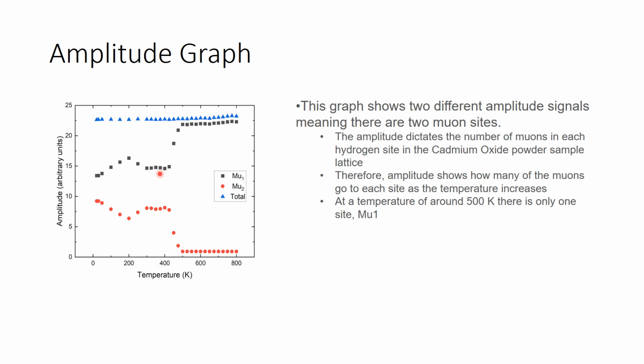As the temperature increased, the total amplitude, as seen by the blue, was all converted to mu1, so that means that all of the muons started to go to the mu1 site as the temperature increased, whereas as the temperature increased past around 500 right here, the mu2, the other hydrogen site, none of the muons seem to go to that one.